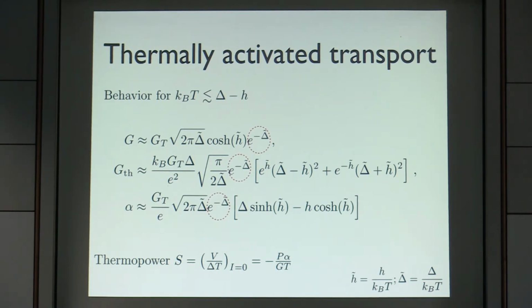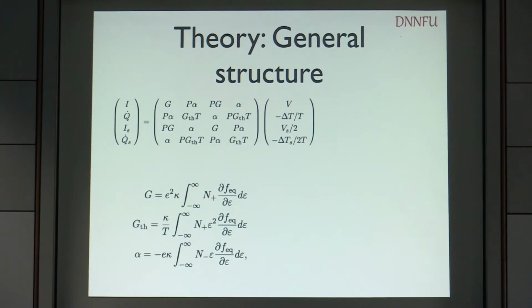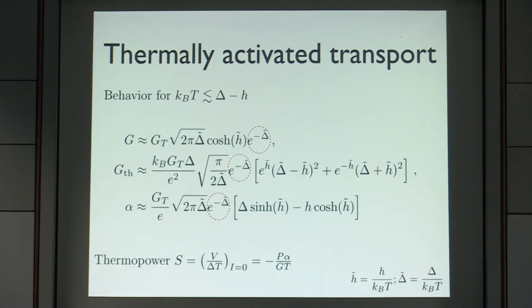It's just a tunneling model with a superconductor, so you can actually do pretty good analytics. Basically, what you do is replace the derivative of the Fermi function, which is 1 over hyperbolic cosine squared, typically with an exponential in the case when you have a gapped density of states, like in our case here. Then you can calculate these integrals completely analytically, and you get these results. In particular, since you have a gap dispersion, you get Arrhenius-like results where you always have e to the minus delta over T in these expressions.